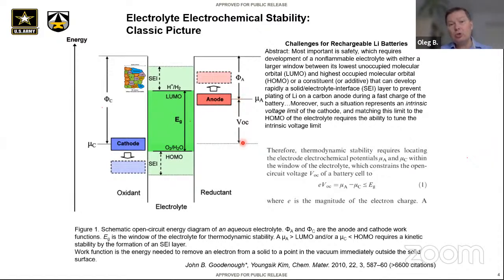and that gives rise to the electric voltage between two systems, which is OCV, roughly voltage. In order to choose an electrolyte, we can go two ways, right? We can choose a very low voltage between the cathode and anode, then electrolyte would be stable. So, for example, if the anode has a work function which puts it lower than the chemical stability, electrochemical reduction of electrodes and electrolyte, then electrolyte doesn't reduce and it's stable. Once we put the anode higher, electrons from here want to jump to lower energies, right? So electrolyte reduction will be happening.